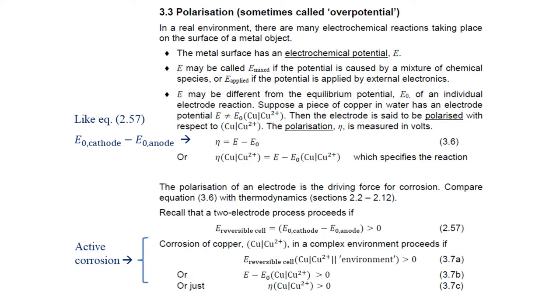Now, when the cathode is a complex environment rather than just one reaction, we said we imagine measuring the potential of the cathode, and then we evaluate the reversible cell potential as in equation 3.7a. Then on page 20 we argued that the prediction made by equation 3.7a is the same as the prediction made by equation 3.7b, which asks the slightly simpler question: is the surface potential more positive than the possible copper anode equilibrium potential? If so, then we predict there is still a positive reversible cell potential and the copper corrodes.